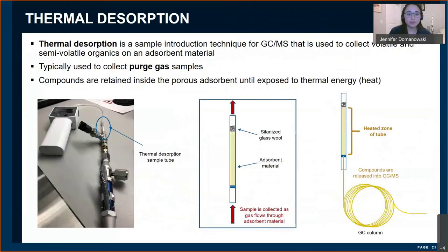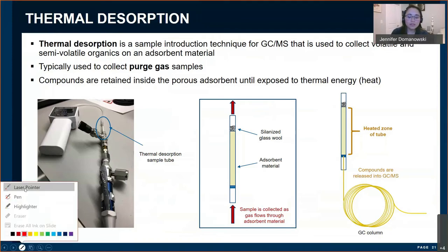Thermal desorption is a sample introduction technique for the GCMS. So this is mainly used to collect volatile and semi-volatile organics. And a lot of what we use this for is with purge gases. So purge gases are typically used for keeping flight hardware clean and dry. And this is especially important when you're working with lasers or optics, things that are very sensitive. So we use this technique to make sure that our purge gases are clean and we're not introducing any unwanted contaminants to our hardware.